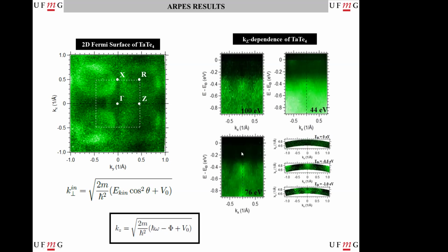We measured for different values of photon energy, and we can see that the states are present even when we change the photon energy. And this is the image we got when we apply this formula, the relation between the momentum kx and kz, the perpendicular momentum. Here is the dispersion obtained at the Fermi level. Because of the region of reduced spectral weight, here we can see nothing, which was expected.